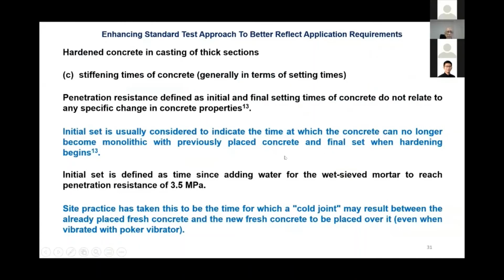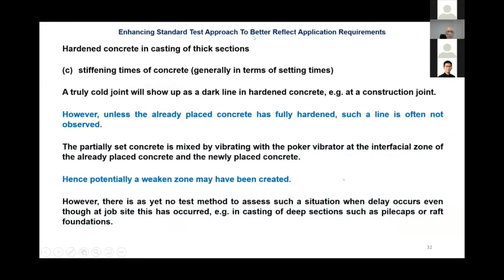So stiffening time or the setting time is penetration resistance. The initial setting time at 500 psi or 3.5 MPa is deemed to be critical. That might end up having a cold joint. Now this is a practical observation, or shall we say by choice on site, not because it has a particular meaning. I think our speaker later on will tell us more about how concrete stiffens, and you will understand this much better.